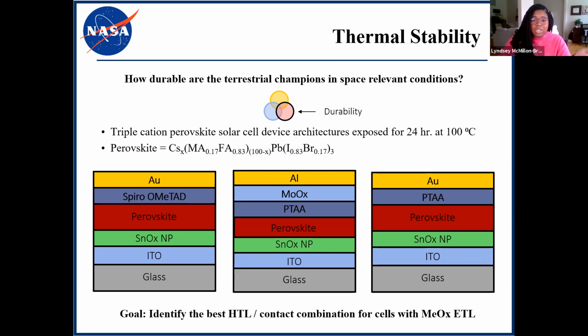And we're going to expose these cells for 24 hours to 100 degrees C. It's generally accepted that Spiro and PTAA are not very thermally stable, so we don't have too high hopes for these. But we would hypothesize that the PTAA, the device shown in the middle, would probably be our best performer because the organics content is kind of encased in metal oxides in this device.